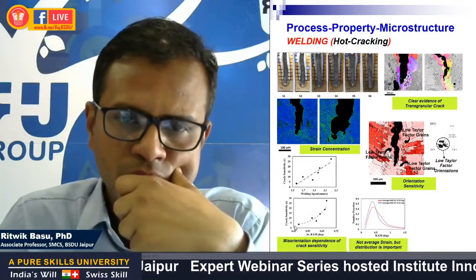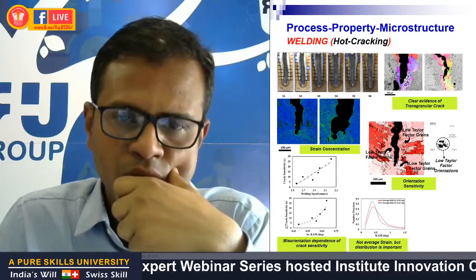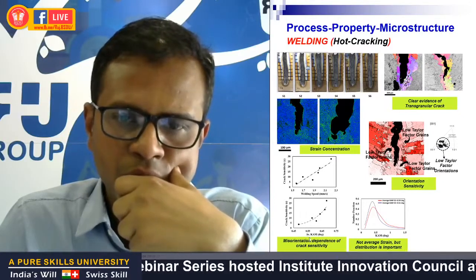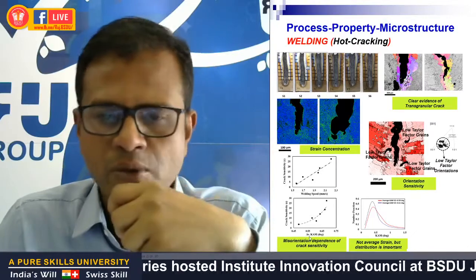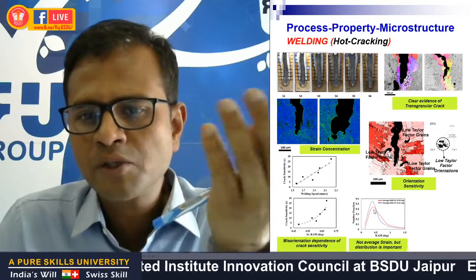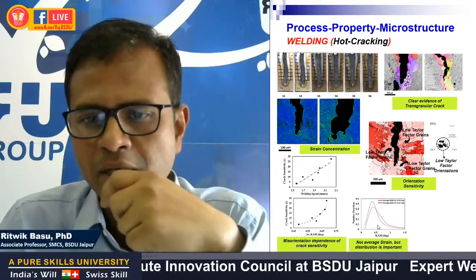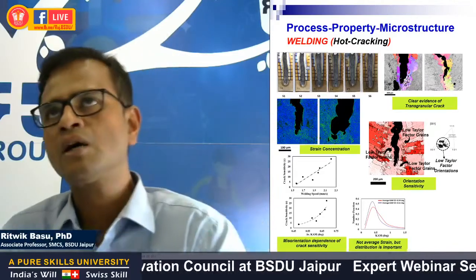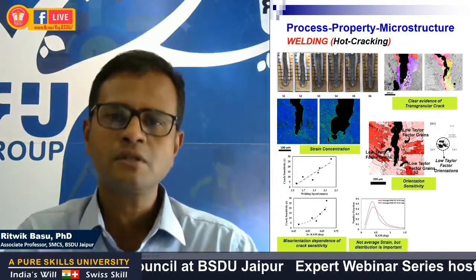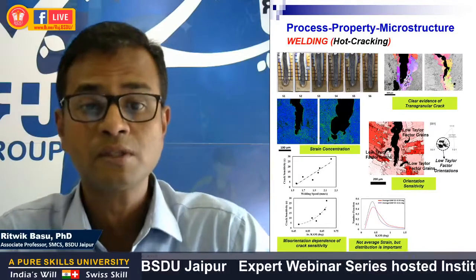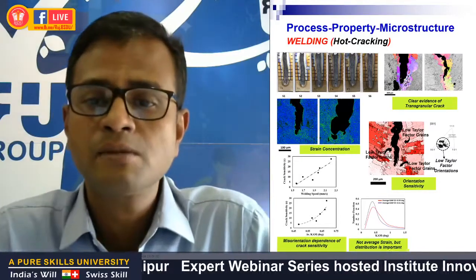So we also found that this crack sensitivity not only depends on the average misorientation of the weldment microstructure, but also depends on the distribution of the misorientation in the microstructure. That means how your defects or dislocations are distributed in the microstructure. That also decides the crack sensitivity in these materials.